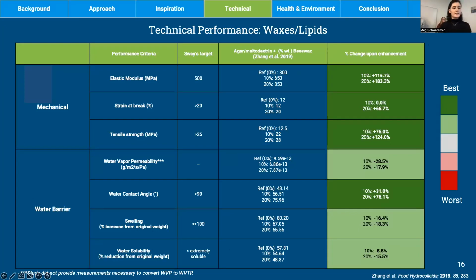So for our waxes and lipids strategy, we're focusing on beeswax as an additive to increase the hydrophobicity of the film. In the study that we present in this table, they were looking at how increasing the concentration of beeswax in their agar and maltodextrin emulsion film could enhance the mechanical and barrier properties. To make these films, they blended together agar and maltodextrin and added 10 and 20% beeswax by weight into the solution. And then they used the casting method to actually form the films.